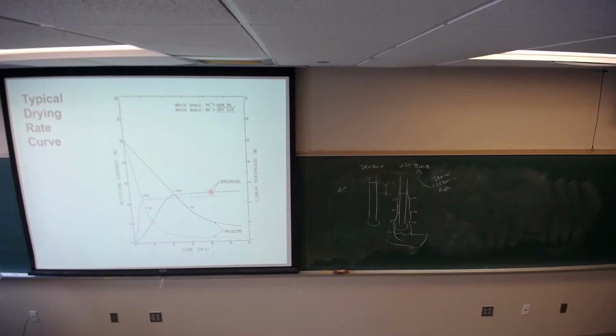But I will tell you from interaction with factories, things are going along just fine, okay? And then everything starts to crack, and the immediate response is to go adjust the conditions in the dryer. But my take is that nothing else has changed. Weather front moves through, changes humidity. Well, that could affect it because you have incoming air. Change in barometric pressure, not sure how that would affect it. Small change in the ability to evaporate moisture. Changes in temperature, no, I'm heating the air, so it doesn't make any difference. There was a change in the process someplace up the line, upstream, that caused the problem.